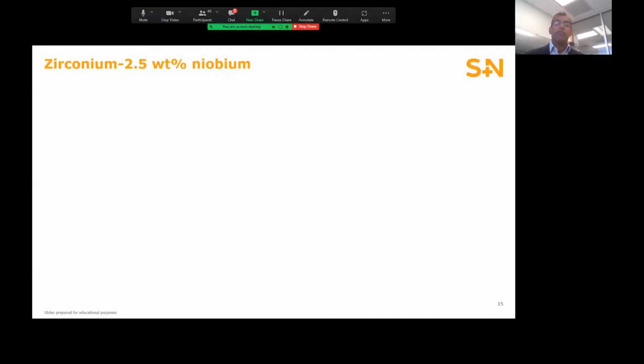So around the same time, Smith and Nephew was investigating the use of the metal alloy zirconium 2.5 niobium due to its suitability for surface hardening. Zirconium alloys were already used in the nuclear industry due to the fact that they would readily oxidize and are corrosion resistant.